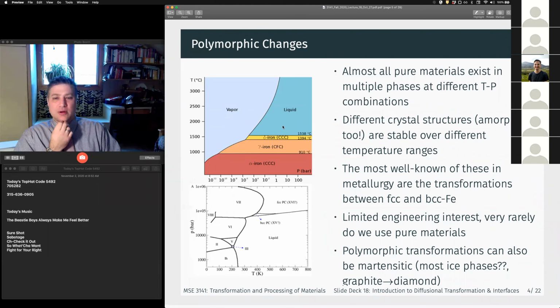One of the most technologically important ones is, of course, the phase changes that are exhibited by iron as we go through the temperature range at atmospheric pressure, right? At low temperature, we are BCC, and at higher temperatures, we go through an FCC back to BCC to liquid. If we go up in pressure even more, we get to epsilon iron, a hexagonal phase. We have many different allotropes of water depending on the pressure and temperature. Most of these are not particularly useful for engineering purposes because most of the time we're not dealing with pure